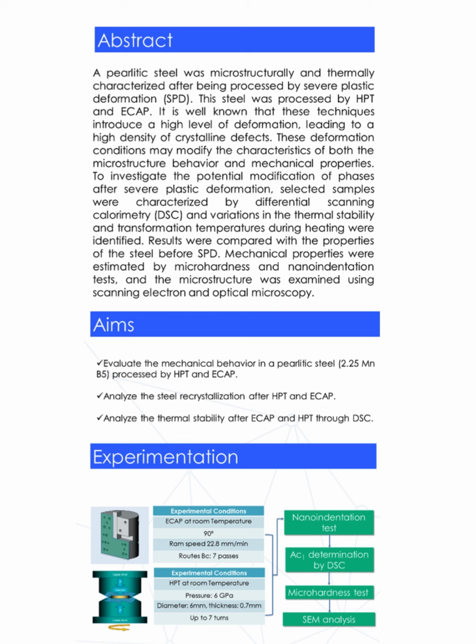This study explored how these deformation processes affect the steel's microstructure and mechanical properties. Differential scanning calorimetry, DSC, was used to characterize selected samples, revealing changes in thermal stability and transformation temperatures during heating. The results were compared to the steel's properties before undergoing SPD. Additionally, mechanical properties were evaluated and the microstructure was observed.